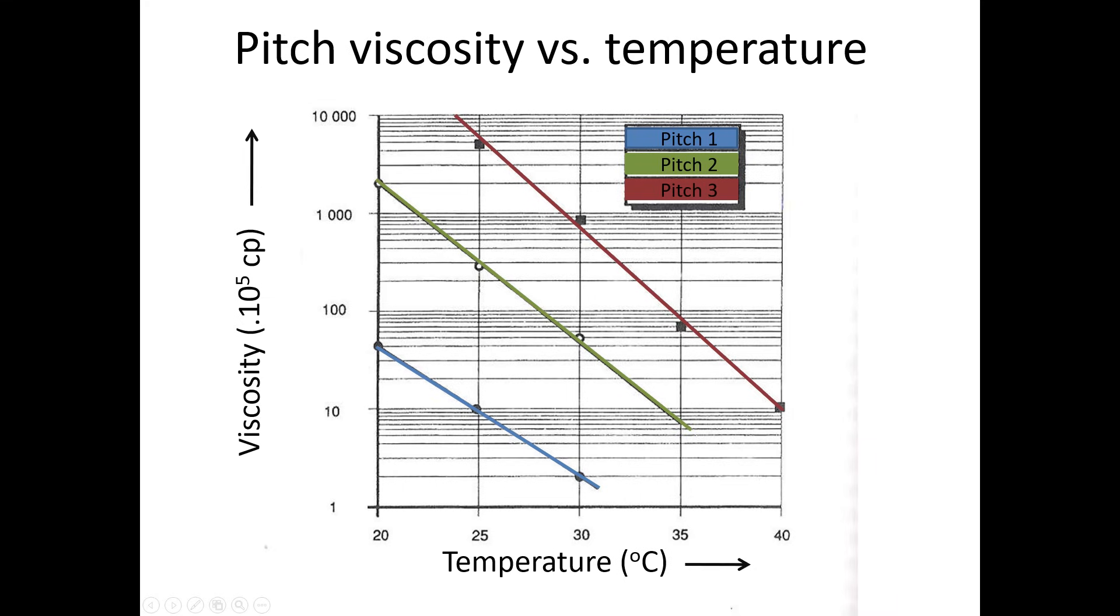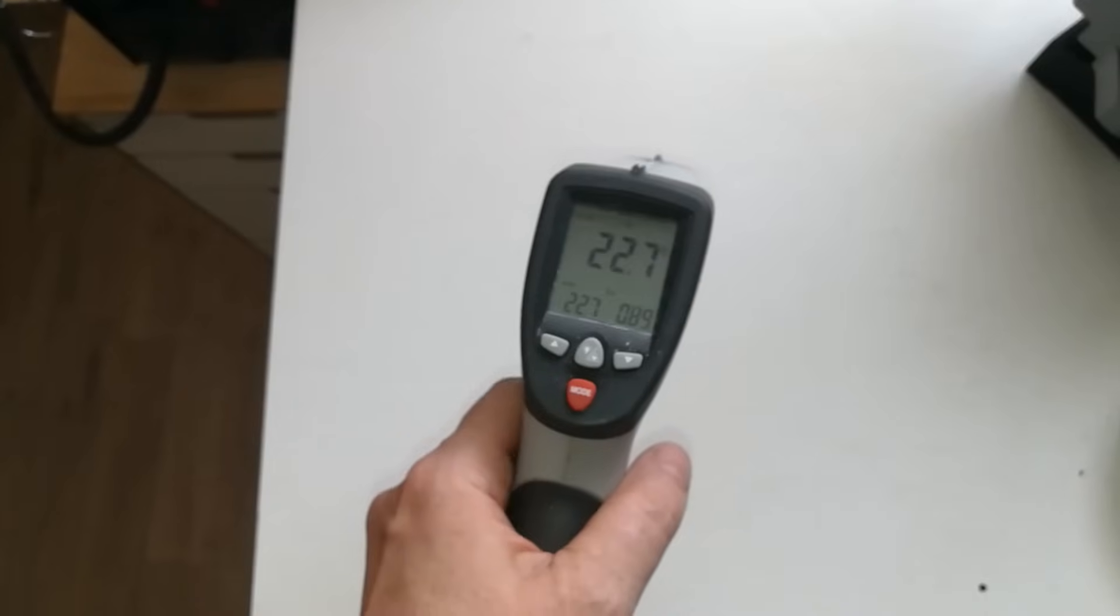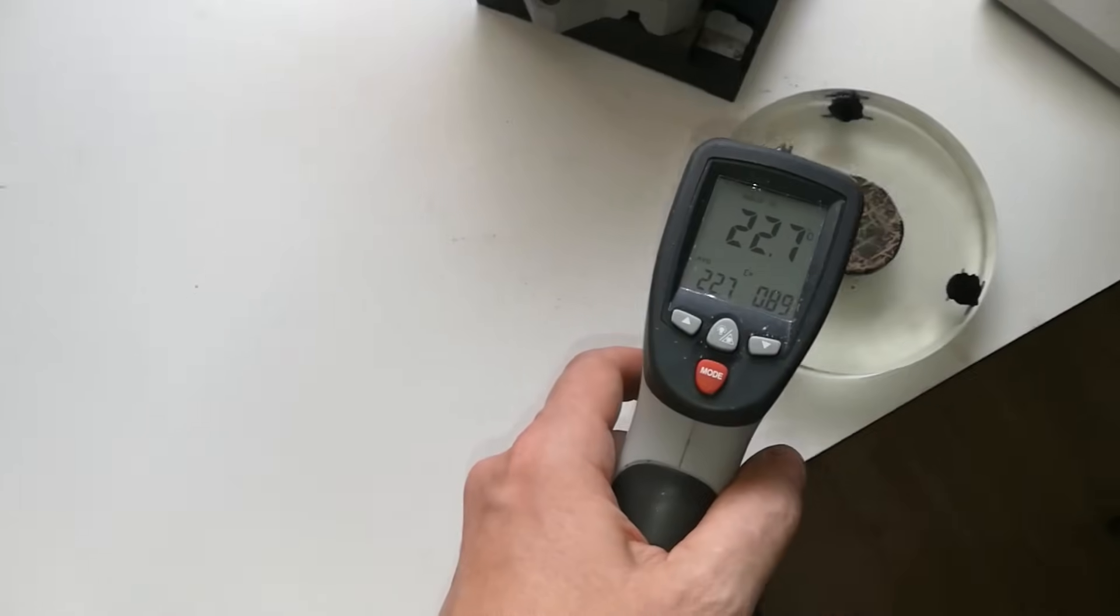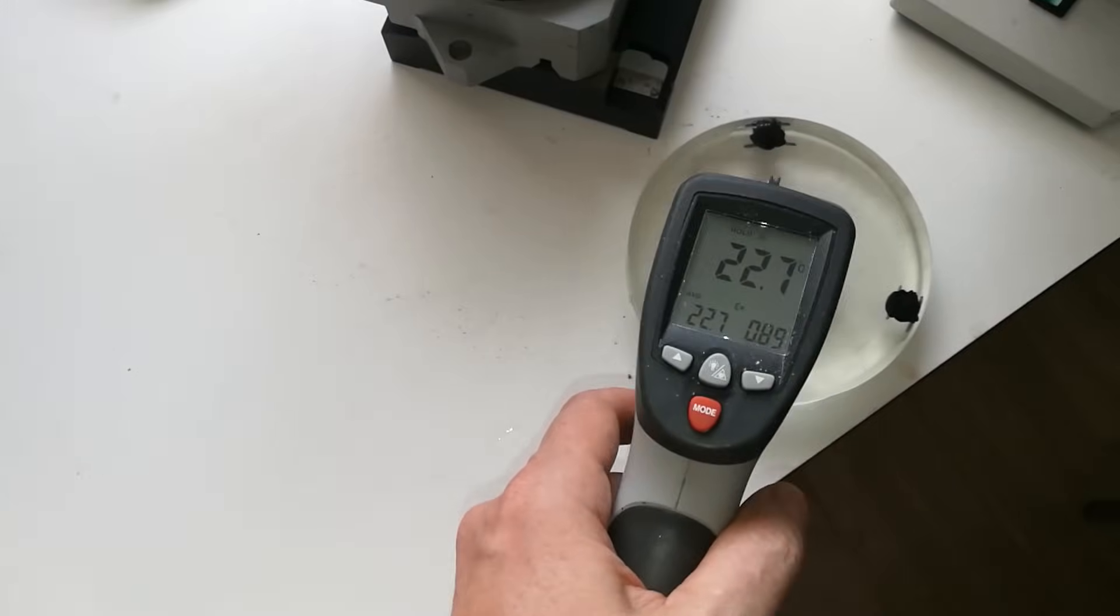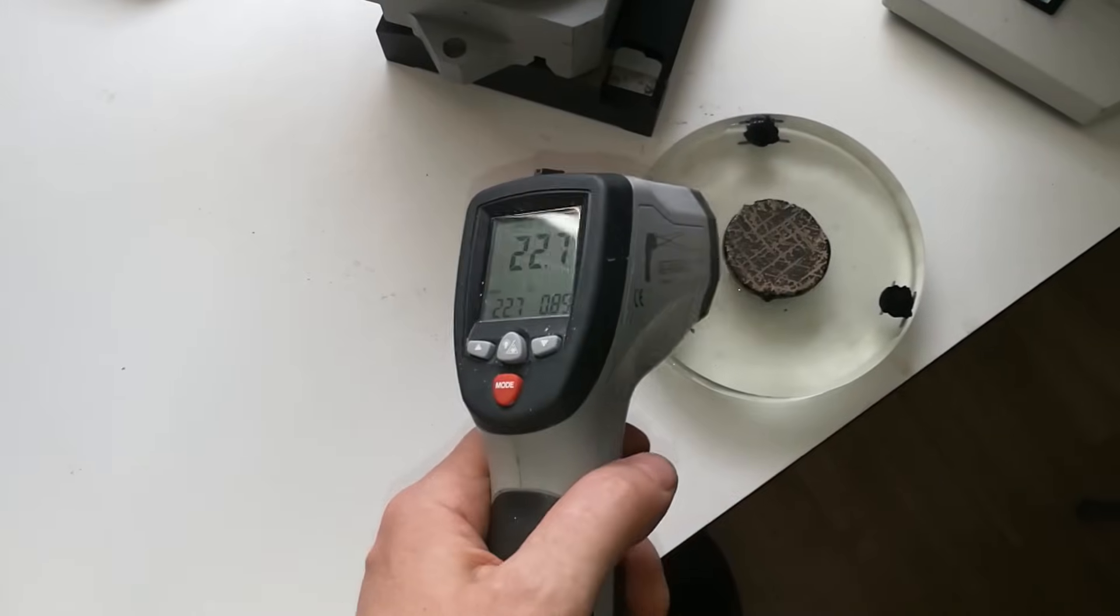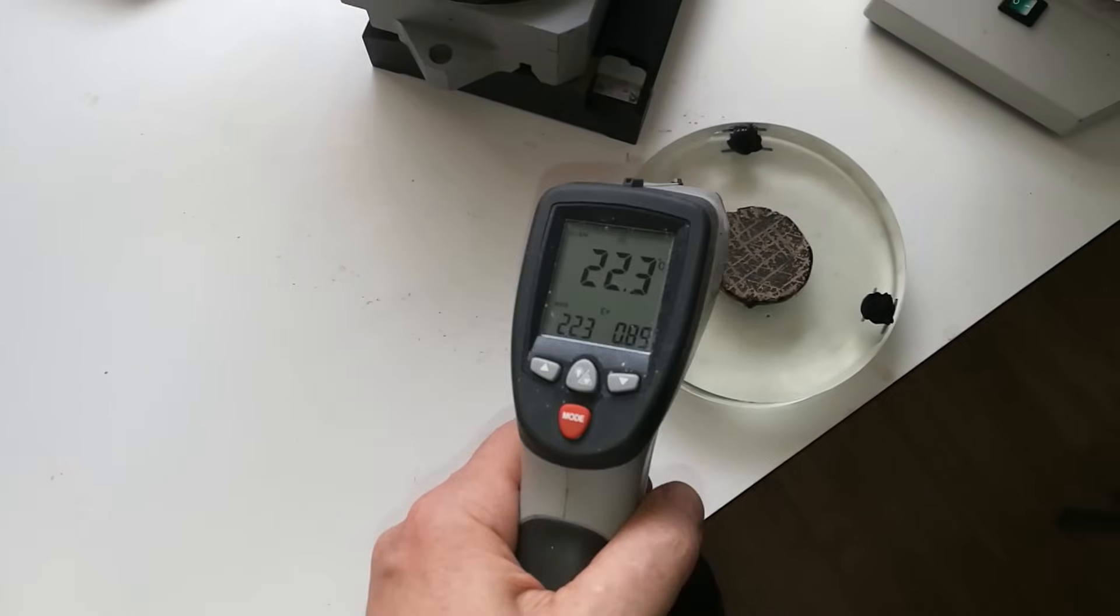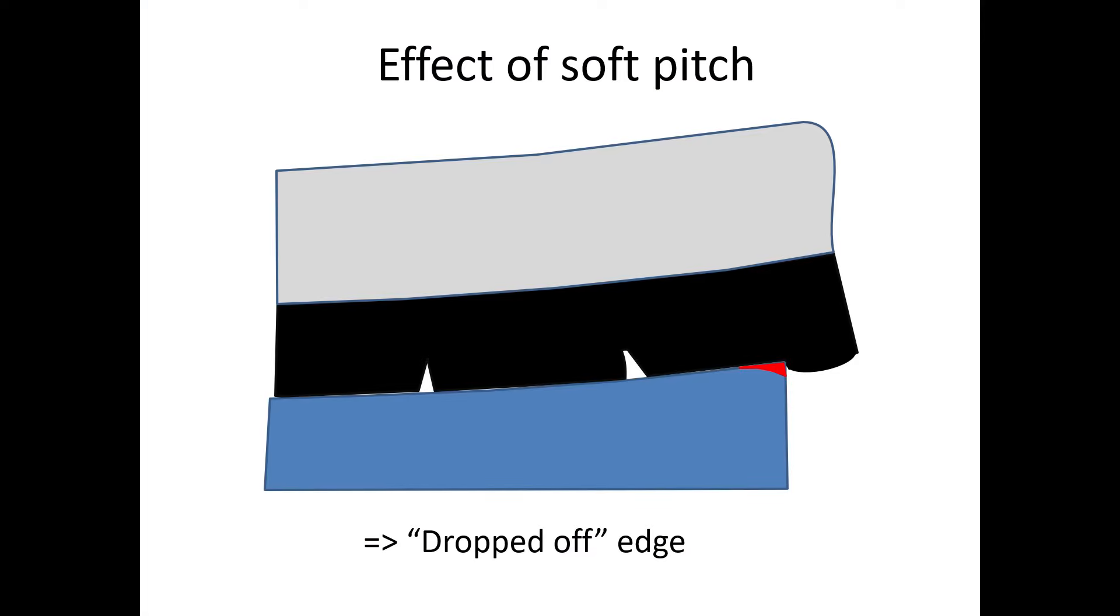Pitch is actually a very high viscosity organic resin, generally made from trees. The viscosity of the pitch however is strongly dependent on temperature and it can change a factor of 10 over a range of only 10 degrees easily. This means that if we want to do well-defined polishing, we should use the pitch at a very well-defined temperature. If the pitch is too warm, deformation of the pitch occurs too easily and this can strongly enhance polishing rates at the edge of the object, resulting in a so-called dropped off edge, which is highly undesirable and can take a long time to remove.